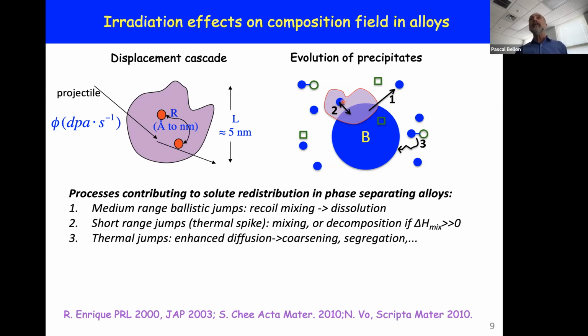In a very reactive system, it may favor the precipitation, as we'll see later. And then there's a third process which will always promote growth, which is the thermally activated transport of solute atoms back to the precipitate. Here we are envisioning a situation where, operating at equilibrium, the system, due to its thermodynamic nature, would want to form stable precipitates. So we have these three processes: medium range ballistic jumps, short range jumps, and thermal jumps.